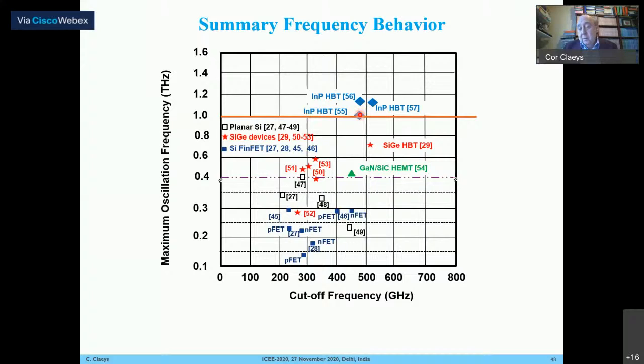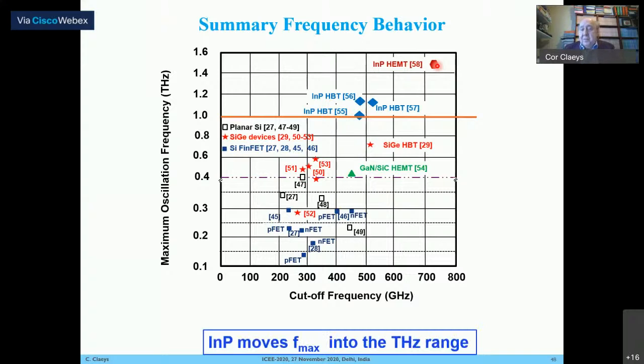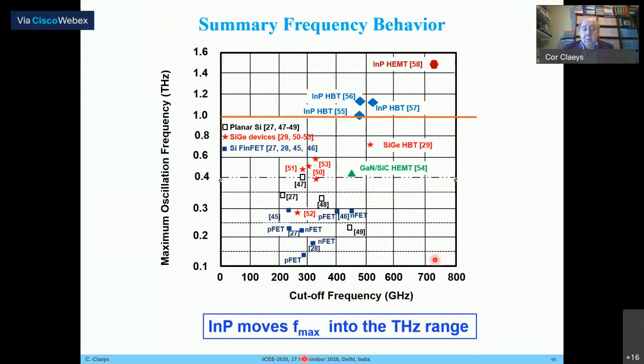And you see that we are entering the terahertz region. The best device reported so far that I could find is an indium phosphide high electron mobility HEMT, where you get about 1.5 terahertz for Fmax and 750 gigahertz for the FT. So using indium phosphide is moving Fmax into the terahertz range. And then keeping in mind what I mentioned a moment ago, that you can finally work with indium phosphide on silicon, I think there is a very bright future for new types of high frequency devices.